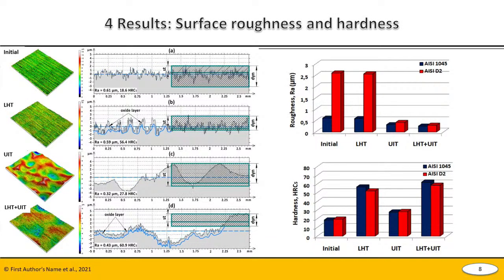The typical surface texture and profiles after the applied surface modification methods you can see on this slide on the left. Regardless of the initial surface roughness, the combined treatment provides an average surface roughness of about 0.25 micrometers due to a specific micro-relief formation. At the same time, the surface hardness was increased by more than twice after combined treatment. This is because the severe ultrasonic surface deformation caused a refinement of martensitic grains in the near surface layer formed by the laser transformation hardening process. Next slide, please.